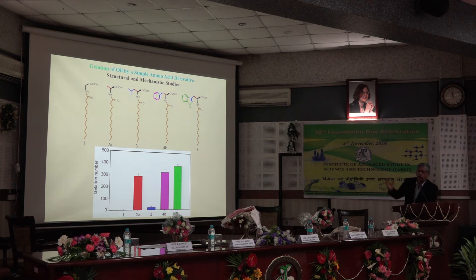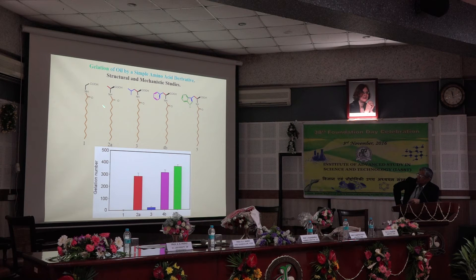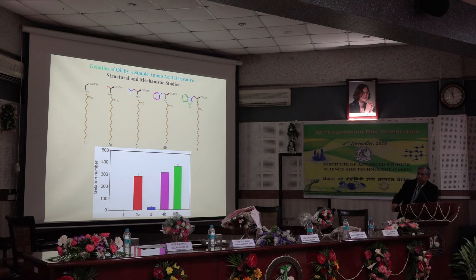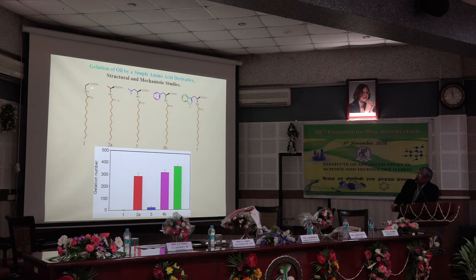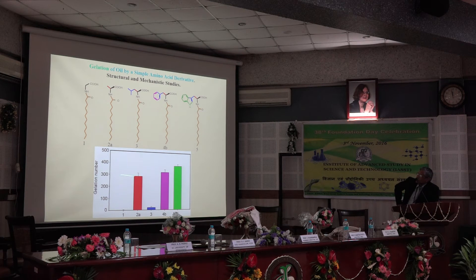Another example: very simple amino acids — these are natural amino acids, fatty acylated products, like biosurfactants. This is very important in this part of the country, where you have plenty of flora and fauna where you could get this kind of biosurfactant. Now we find that these molecules have very different behavior in terms of gelation. If you take one or two milligrams and dissolve them in toluene, you can see when it is glycine, it does not gelate.